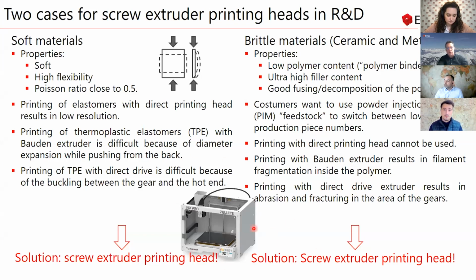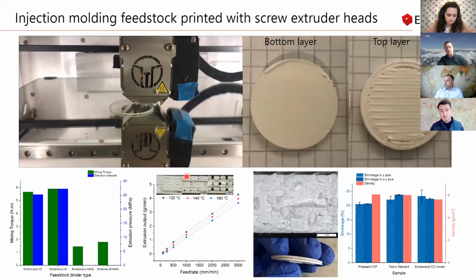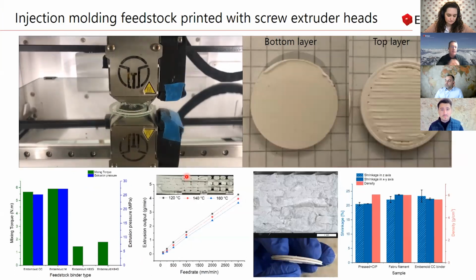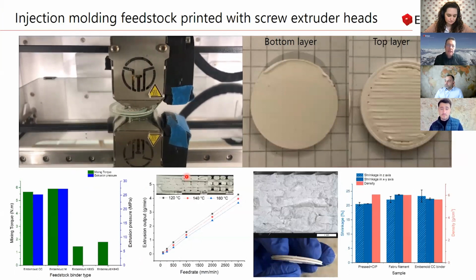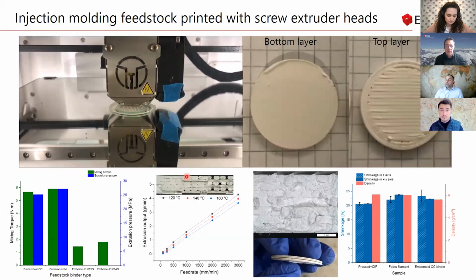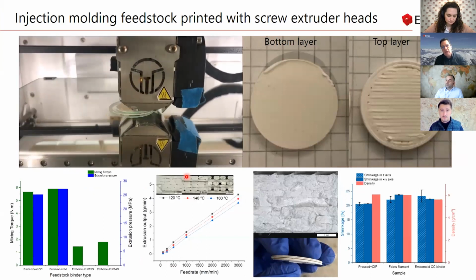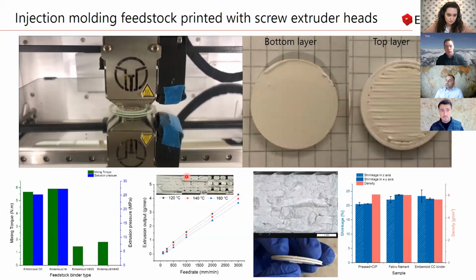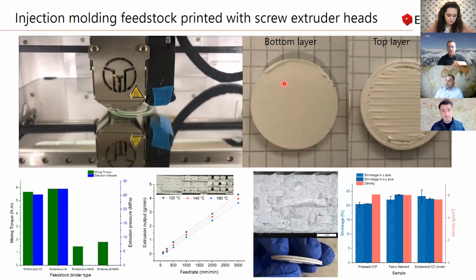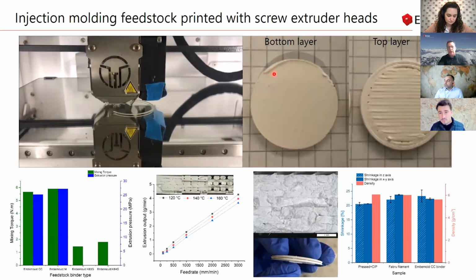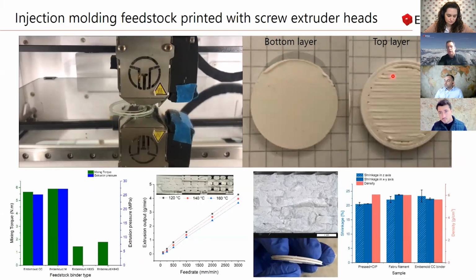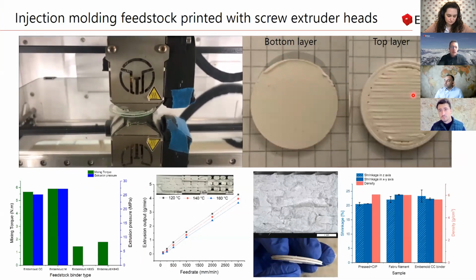So these are two material classes where the screw extruder printing head makes sense from our perspective, and where we already use these materials. And here you can see now some work which we already did in the last years. So this is, for example, a pellet extruder which we have here. And with this pellet extruder, we printed some discs, first of all. And you see here the bottom layer, which is quite smooth. The top layer is a little bit rougher.